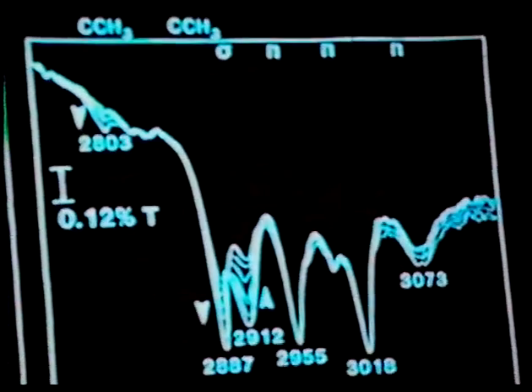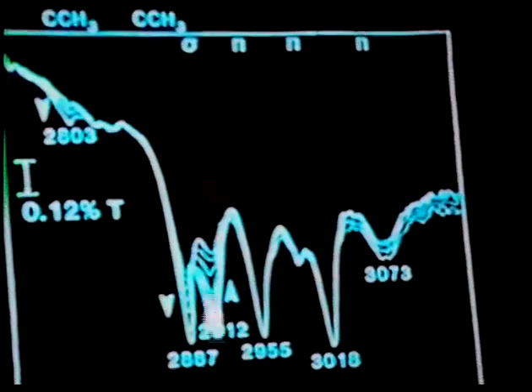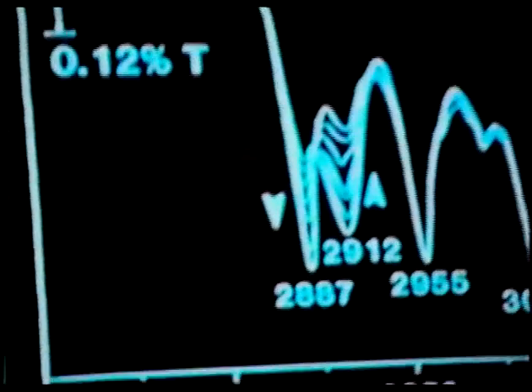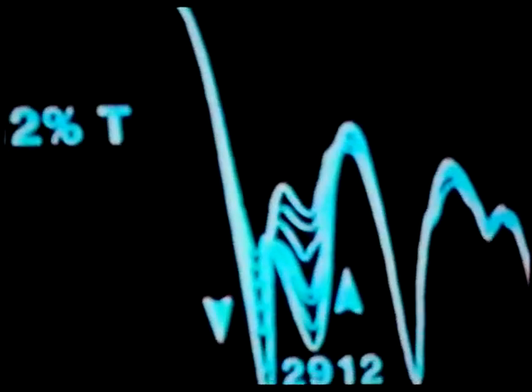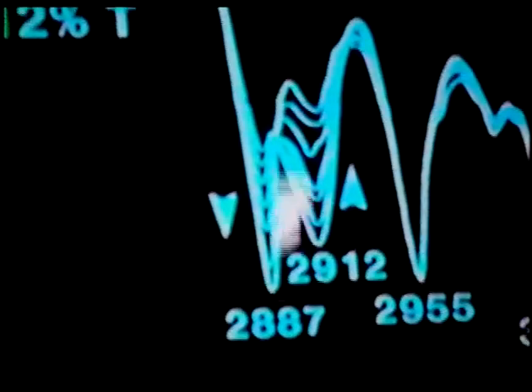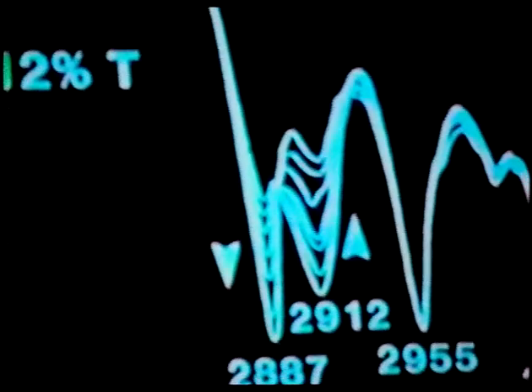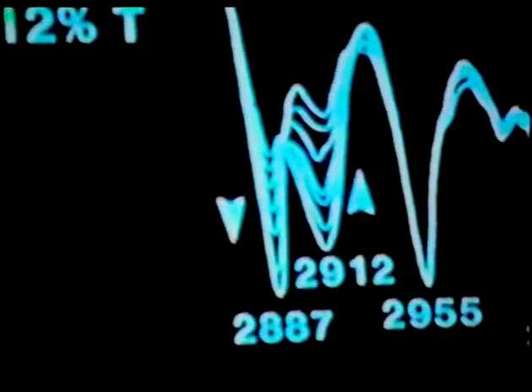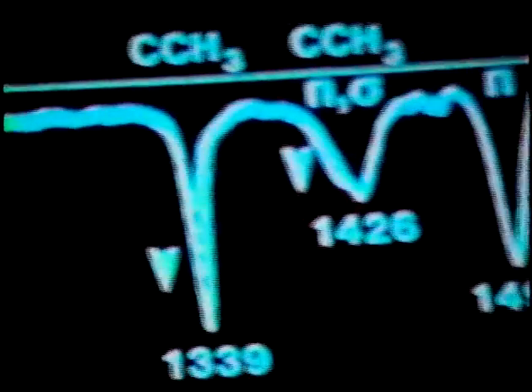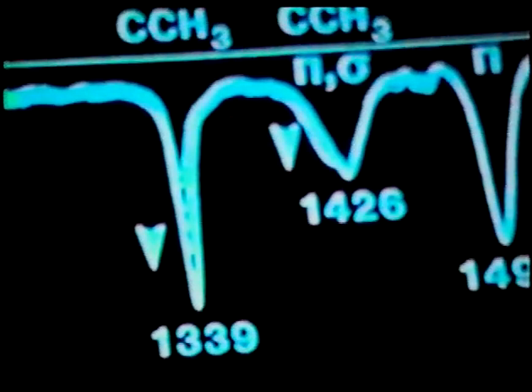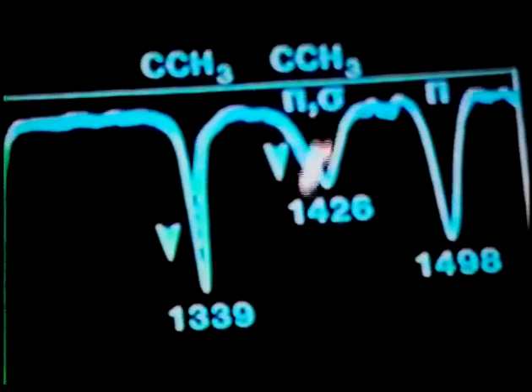Out in here, there's some changes due to differences in the removal of the background, but by and large, these bands are unaffected. However, as you can see, the 2912 band, due to the di-sigma-bonded ethylene, is decreasing, and at the same time, the bands due to the formation of ethylidyne are growing in. And you can see that across the entire spectrum. This region here, this 1426, probably has 3 overlapping contributions, and you can see that a little bit of the edge here is beginning to grow in.